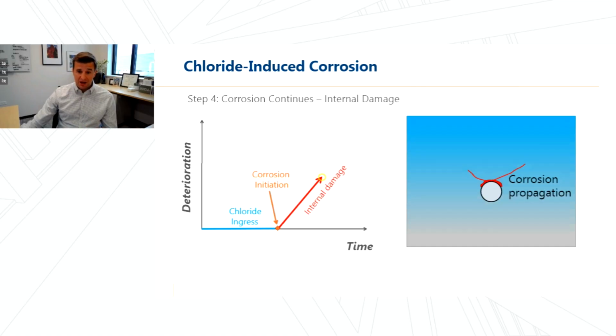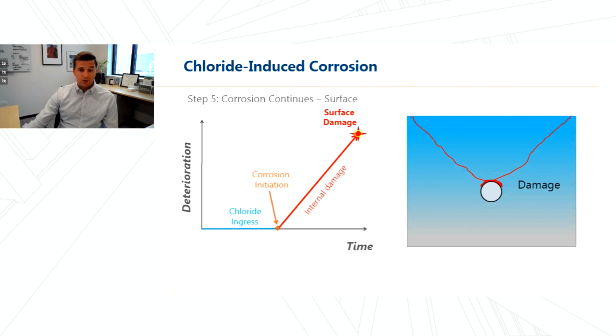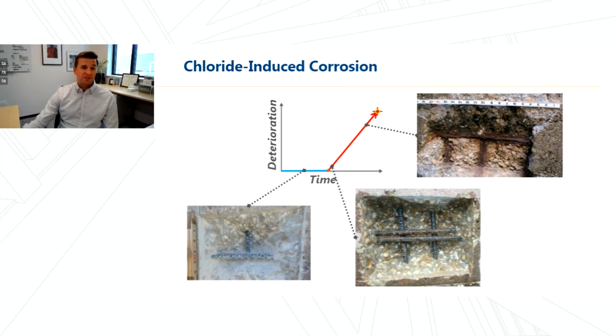Given adequate supply of oxygen and moisture, the corrosion reaction will continue, and that expansive nature of the reinforcement that we talked about earlier can cause internal cracking, and in many situations can propagate until we have surface damage, revealing itself in the forms of cracking and spalling. And we observe this on real structures. These are 3 photos taken from the same structure at strategically positioned inspection windows such that we could capture the range of expected conditions. So now let's continue to look at this behavior on a real structure.